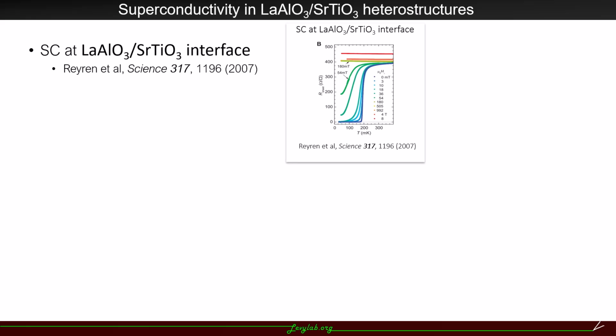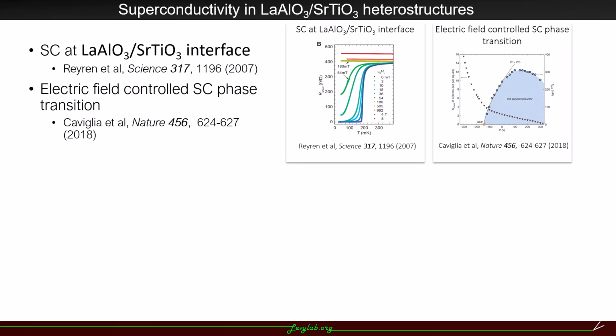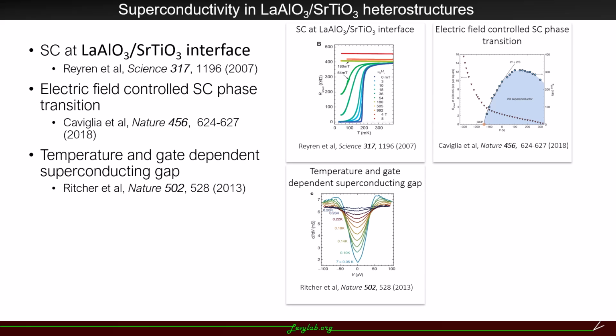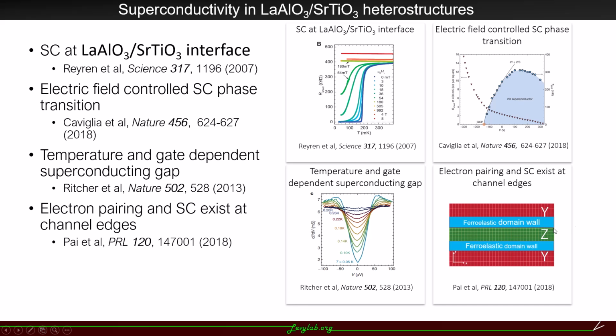It has been found in 2007 that this heterostructure undergoes a superconducting phase transition at around 200 millikelvin. Critical temperature can be controlled by electric field, and the phase transition diagram is shaped like a superconducting dome. In the system, people have also found temperature and gate-dependent superconducting gap. These are interesting features that are similar to what's been seen in high-temperature superconductors.